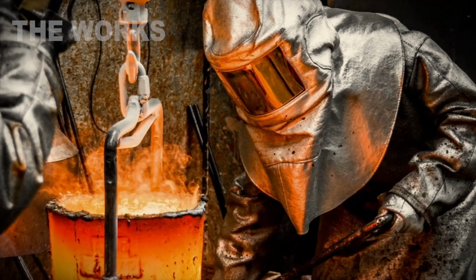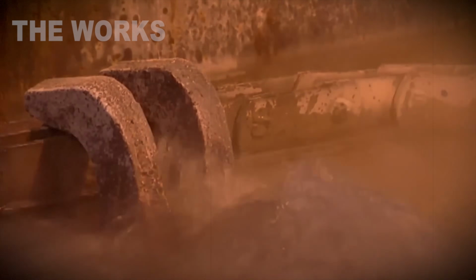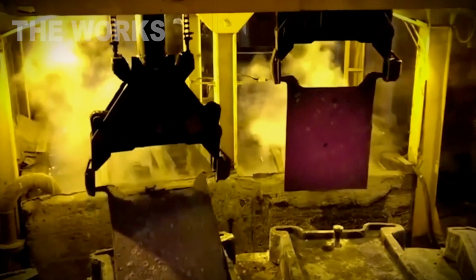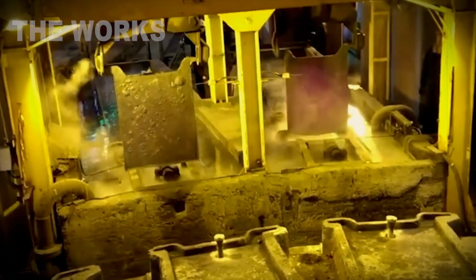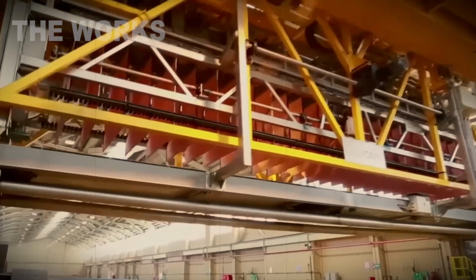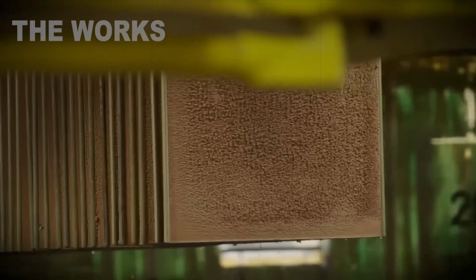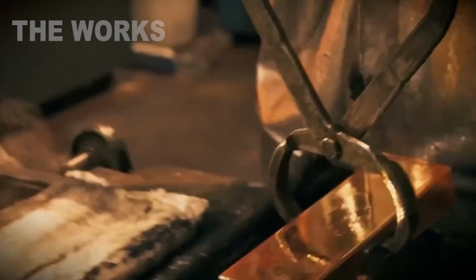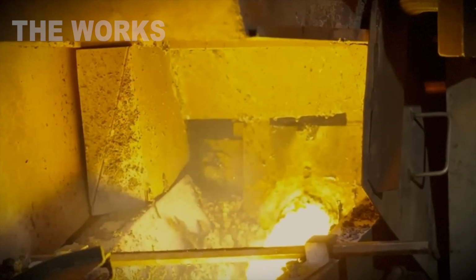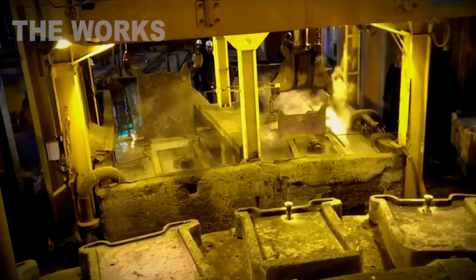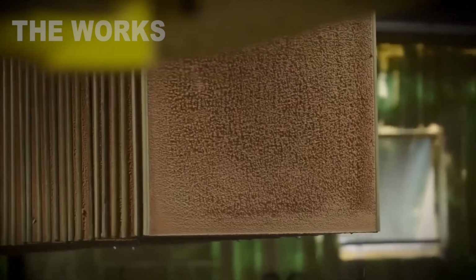Copper dissolves from the anode, travels through the electrolyte, and deposits onto the starter sheet. After 12 to 14 days, a cathode builds up on the sheet, a plate of pure copper weighing 130 pounds at 99.99% metal content. That's grade A, the highest category of exchange copper on the London Metal Exchange.